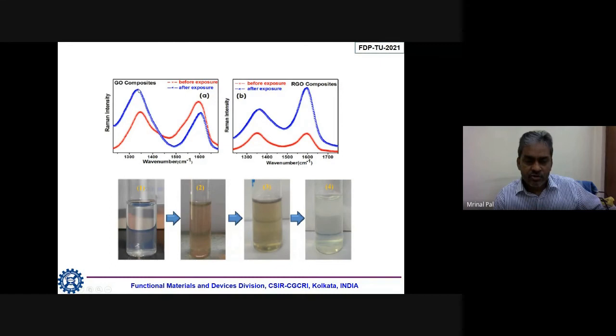They also, after exposure, because of the presence of these silver nanoparticles, because we have exposed them to light, the silver nanoparticles have deposited, so the intensity has increased. And in the case of RGO also the same is noted. And if you look at this solution, you see this was the initial one without exposure, and after exposure it becomes more dark. And this one, this figure 4, is when we have stopped exposing the light. After some time it again becomes very clear. That means that the silver nanoparticles have converted again. So it can be used for photochromic kind of applications. So that is one important study.